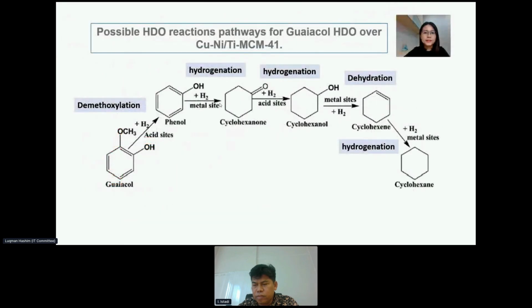Based on the analysis that we have done, the group has successfully summarized the deoxygenation pathway for the conversion of guaiacol into cyclohexane by using our developed catalyst. First, guaiacol will undergo the demethylation process to remove the methyl group through the acid sites of the catalyst, and it will form phenol, which further undergoes the hydrogenation process in the presence of the metal sites of the catalyst to form cyclohexanone, the ketone form.